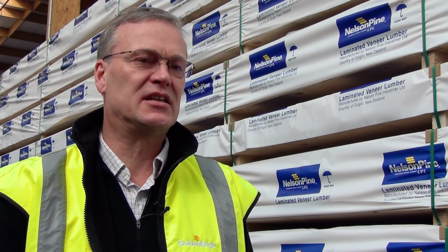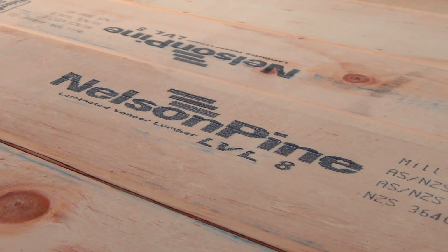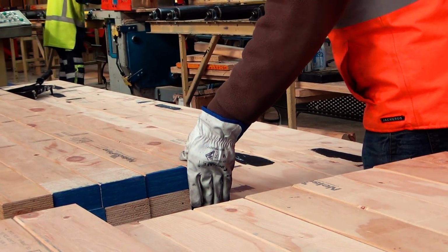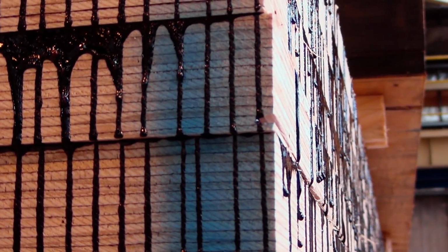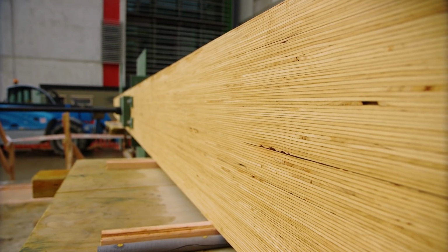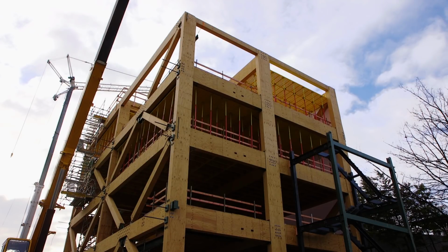We will then use these so-called billets in parts for products like scaffolding or timber, truss and frame and formworks, and other LVL parts will be used in such respect that we will combine them to big timber, as we call it, by gluing them again together with a cold press glue, giving us another A bond, but the timber will be way bigger, up to 30 centimeter thick, 1.2 meter wide, and up to 18 meter long.